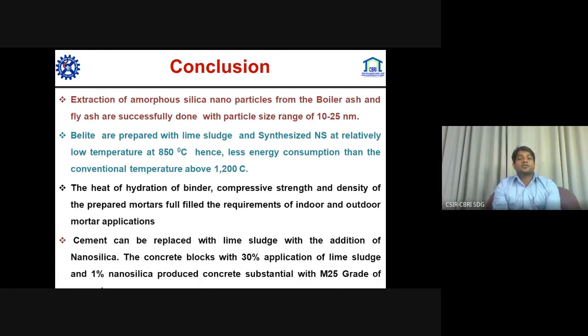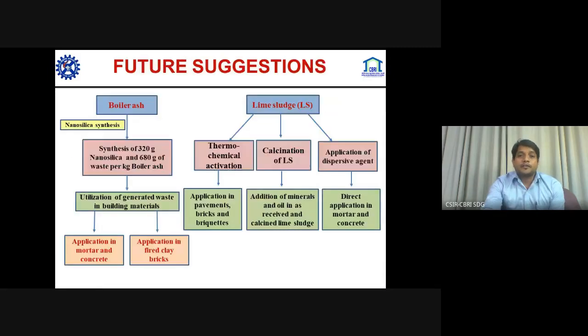The heat of hydration of the binder, compressive strength and density of the prepared mortars fulfill the requirements of indoor and outdoor mortar application. While the cement can be replaced with lime sludge with the addition of nanosilica, concrete blocks with 30% lime sludge and 1% nanosilica can produce the same result in M25 grade of concrete.